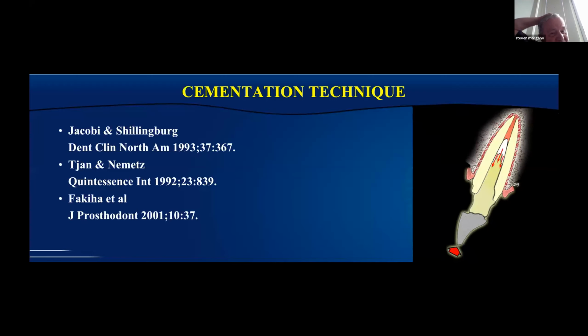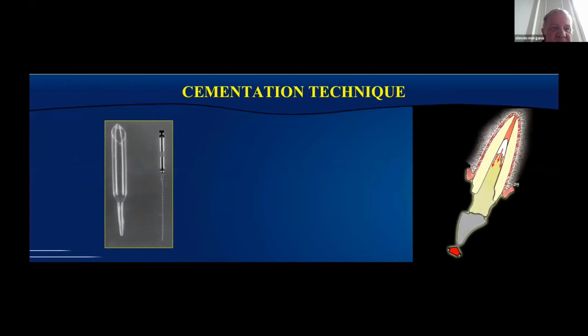Now, Tjan and Nemetz compared Panavia cement, which is a resin cement, to glass ionomer cement, and they had very disappointing retention with the Panavia cement. But when they pulled these posts out, they found air voids, again, about a third of the cement film. So Fakiha has done a study, and it's a really good study. What he found was, if I inject zinc phosphate cement into the canal first, using this Jiffy tube, which is to the left, then I use a Lentulo spiral to make sure that it's adapted to the walls, then coat the post with cement and seat it. Dramatic improvement in retention. Just placing the cement on the post only, and then using these two devices, the Jiffy tube and the Lentulo spiral, improved the retention by almost 3 times.